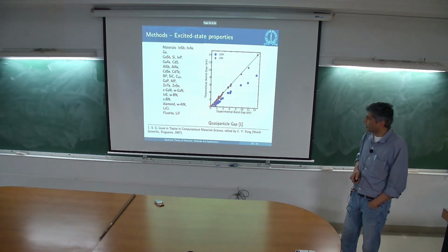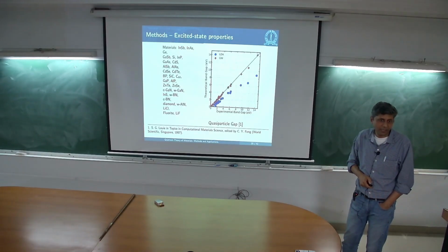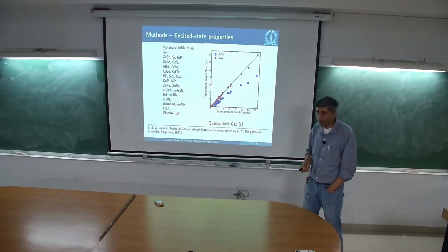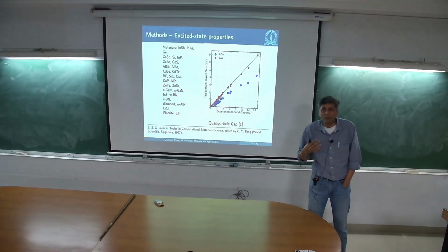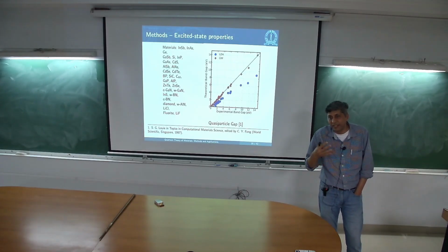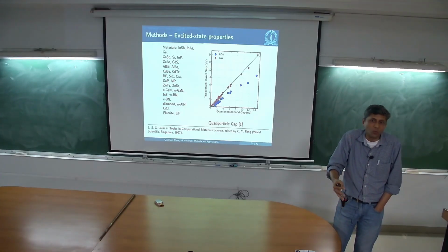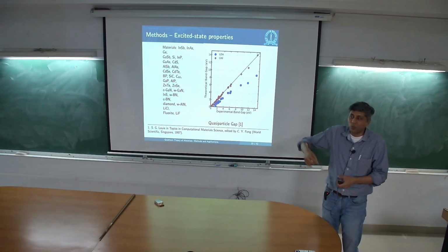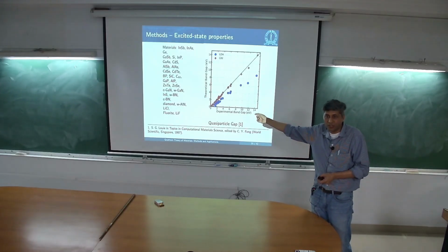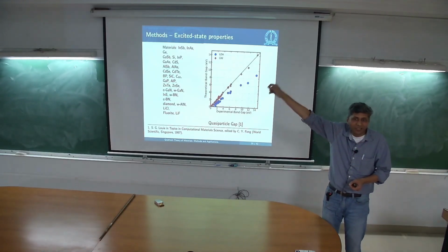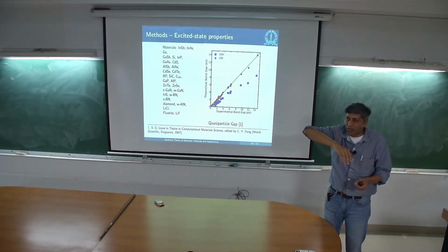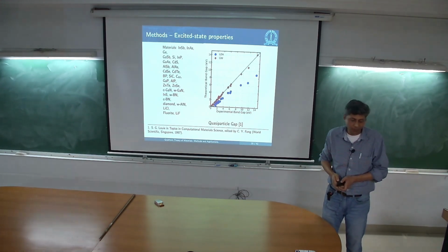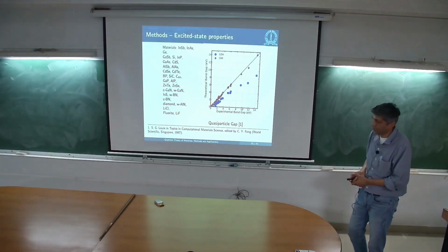If you do the GW approximation, this is what happens, right? So now, all of a sudden, we are doing a lot better than before, and we have a manageable scheme. This is computationally tractable. We can do this on a routine basis, and we have a way in which we can actually try to explain experiments where you add or take an electron out of the system. Experiments like photoemission or inverse photoemission, or places where a change in the electron number would show up. Okay, so this sounds pretty good.